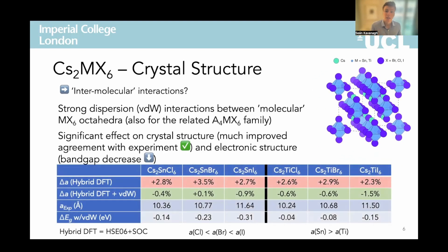Regarding these intermolecular interactions, our calculations reveal significant dispersion or van der Waals binding between the octahedra in this molecular crystal structure, and we've also found this to be the case for related zero-dimensional material families such as the A4MX6 compounds, which are receiving a lot of attention as emerging light emitters. These attractive interactions are found to significantly reduce the calculated lattice constants as expected, and we can see here they greatly reduce the DFT prediction errors in the literature from around 3% to just less than 1%, with an average slight underestimation as we'd expect because of the exclusion of thermal expansion in these geometry relaxations.